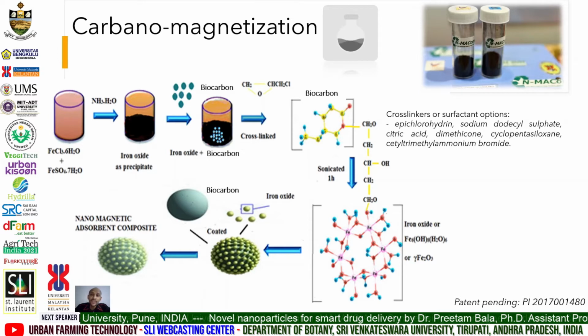Our choices include cross-linkers or surfactants such as epichlorohydrin, sodium dodecyl sulfate, citric acid, dimeticone, cetyltrimethylammonium bromide, and cyclopentasiloxane. This was followed by sonication before separation of the precipitate, which was washed and collected via an external magnetic field. The biocarbon held the magnetic nanoparticles in place, and importantly, no ion leaching was observed before or after use.